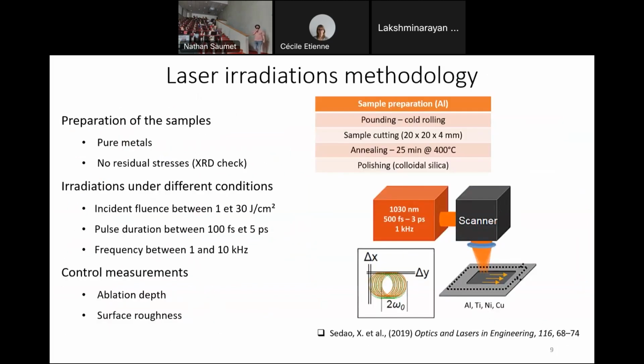Then I will detail some of the methodology used for the experiments. So first, we are preparing samples of almost pure metals in order not to have particles in it, or not to have too many parameters. So we are preparing it in order to have a very polished surface, a very plain surface, and no residual stresses, which we are checking thanks to XRD measurements.